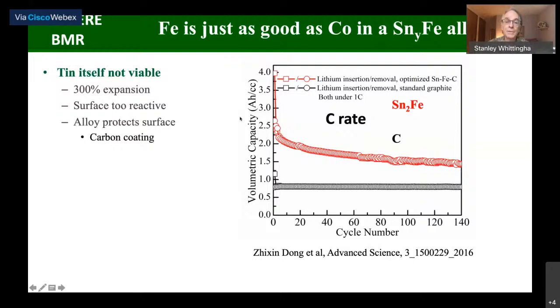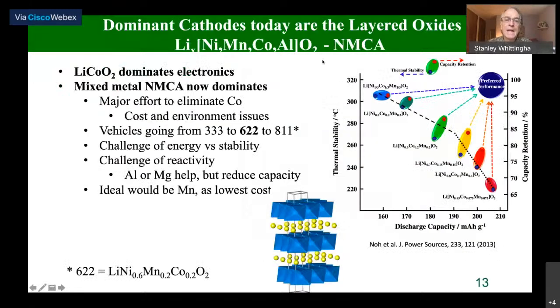So you can see the results on the right here. This is the volumetric capacity, in ampere hours per cc. This is graphite. You can see why graphite is used. Absolutely stable, loses no capacity at all. And here is our tin iron compound. It's more than double the capacity of graphite. And this is at the C rate, which means we're doing the charging in 1 hour and the discharging in 1 hour. So very high rate material, very good material. So we've shown the feasibility of using alloys, but clearly tin is a bit expensive and it's a little heavy in the long term. So let's switch over to the cathode.